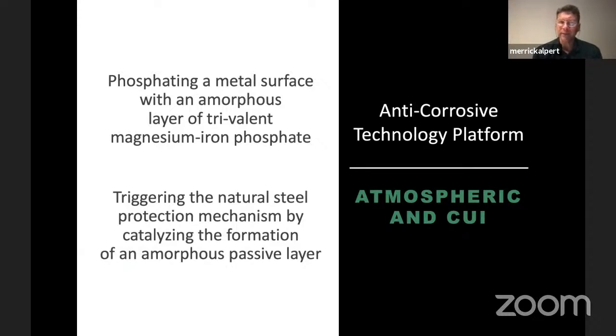On the other hand, we have a high temperature formula. It's often used in two scenarios. The first is corrosion under insulation. And the second is that it is used as a weldable material. When it's used for corrosion under insulation or used on the bottom side, the soil facing side of a tank, for example, that's going to be welded on the opposite side, in those cases, no top coat is used. It's a single coat system. Only the Eoncoat is used. So again, for purposes of this evening's presentation, we have Eoncoat in the atmospheric form and then Eoncoat in a high temperature form used in the corrosion under insulation environment and also used in the weldable environment, most often on the bottom soil facing side of tanks.